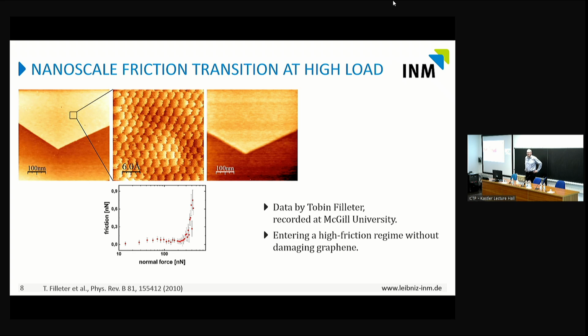And what Tobin did was he went to non-contact mode, and he could image, in the left image, the perfect structure of the graphene. Nothing is really flat graphene, and there's a monatomic step here. Then he would take, with the same tip, atomic stick-slip images at very high load, beyond the threshold. And then he would take the same tip again to do non-contact imaging. Nothing changed. This is not wear. So we have a non-destructive transition to a high friction regime. And we were scratching our heads all the time about what this high friction regime is.